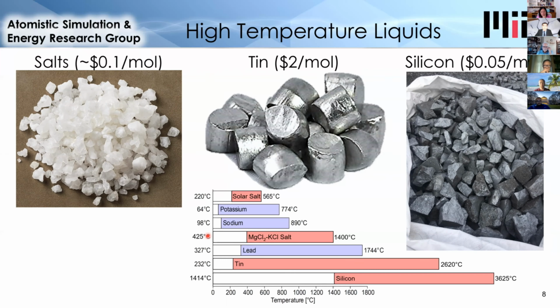Another option is tin, which is very interesting. It's shown here. It has a very wide liquid range, so it melts at a low temperature and boils at a high temperature. It also has high thermal conductivity and low viscosity, so it's really great as a heat transfer fluid. The problem with tin is that it's between 20 and 40 times more expensive than the other two materials on an energy basis, and so it's too expensive to use for energy storage. So it has applications for heat transfer.